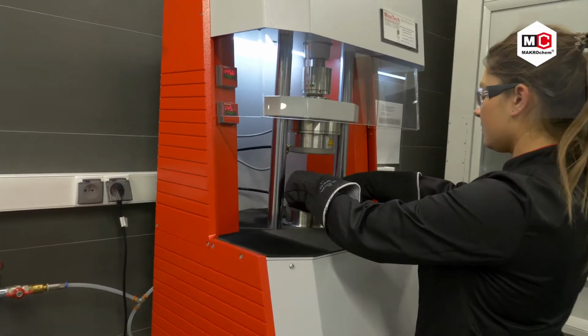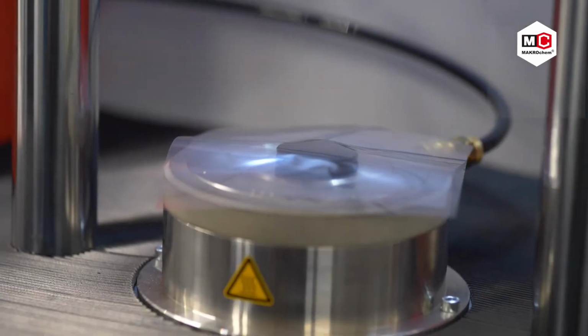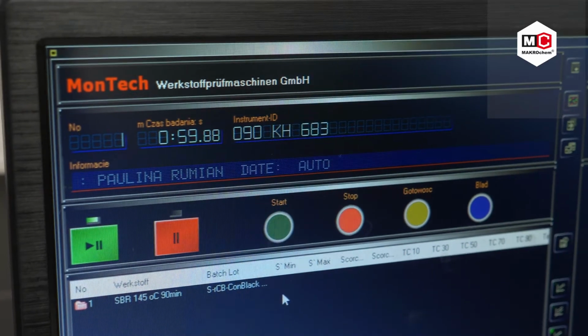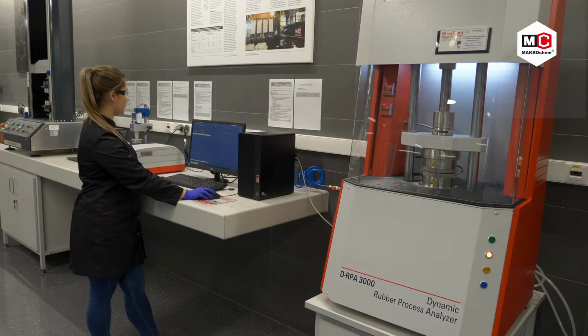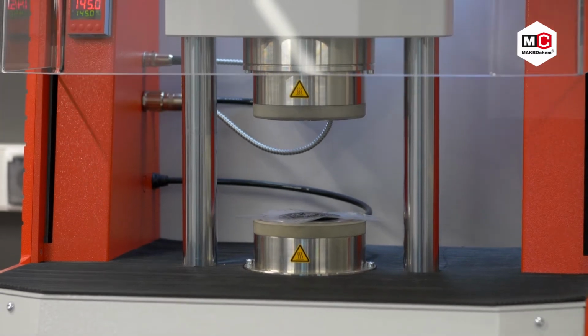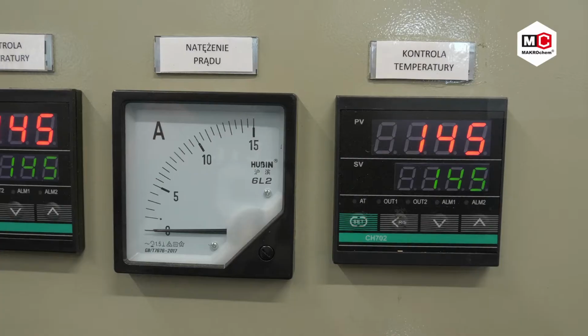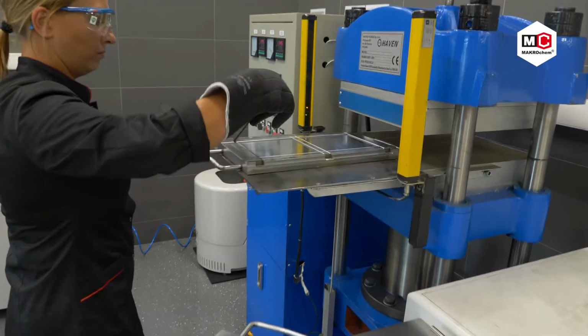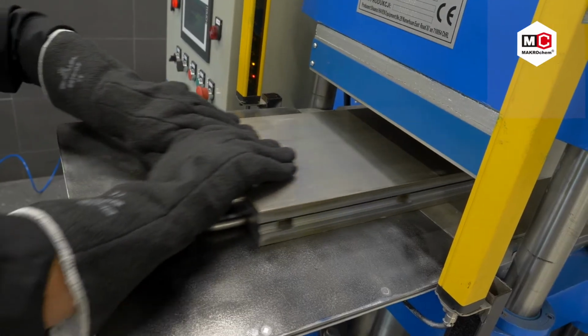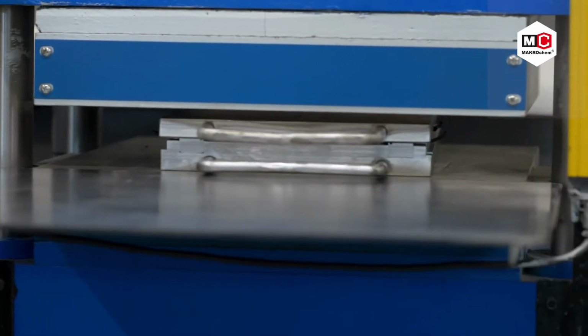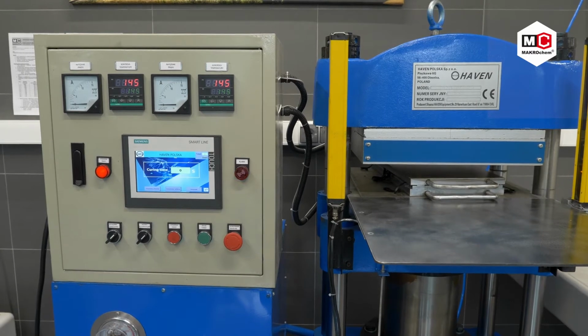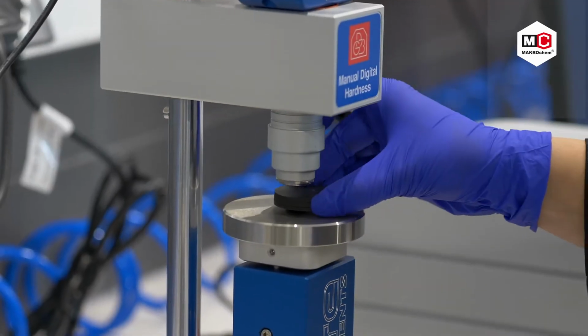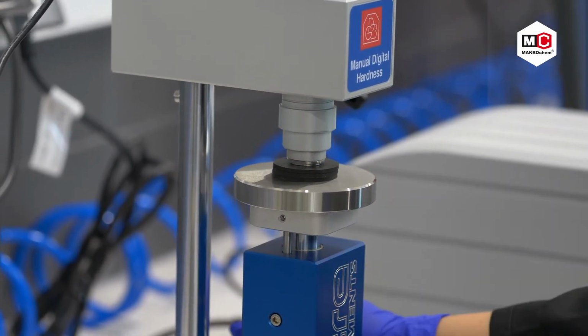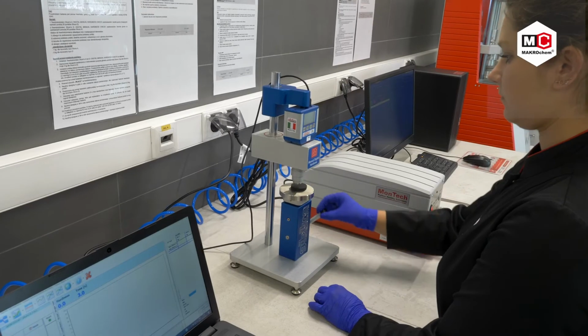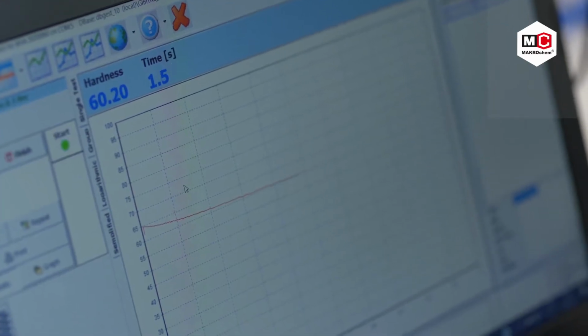Using rheometer, we estimate the kinetics of vulcanization of rubber compound, the value of torsional moment as function of time in given temperature. Based on this, we estimate, among others, scorch time and optimum curing time of rubber compound. A properly prepared rubber compound is placed in a vulcanization mold and pressed in specific temperature and time period based on optimum curing time. In this way, we produce samples of vulcanizite that we test further for physical and mechanical properties. Firstly, we measure the hardness in Shore scale, as it is one of the basic parameters of rubber.